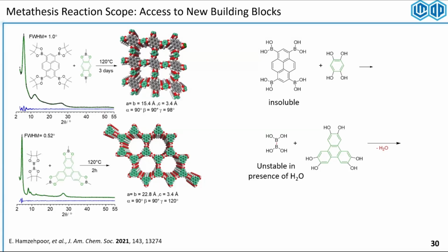And the second case was a tetrahydroxy diboron precursor. And it's fundamentally impossible to make this COF using conventional reactions because this boron-boron bond is highly susceptible to water attack and forming borax.